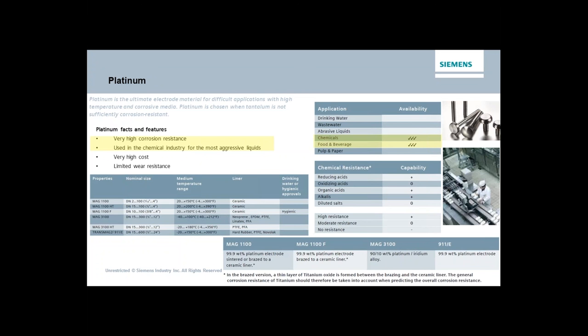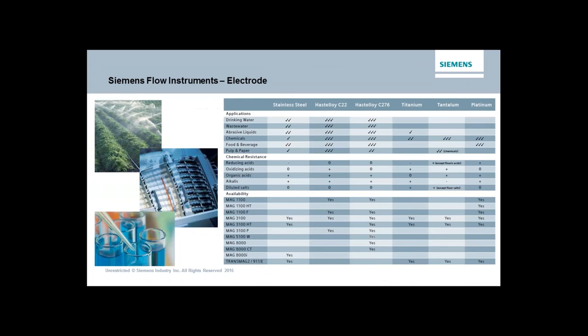You have to be careful when you're looking, for example, at something like a Compass corrosion guide, which is fairly standard, because what they're looking at is pipe. So you're looking at something with a fairly good amount of metal associated with it. If you look at the electrode, you'll see the amount of material on the electrode is not nearly as thick as a piece of pipe would be. So it is possible that you'll talk to a mag meter manufacturer, and they may say, well, we don't recommend this material for this application. And you may have looked it up on a corrosion guide and said, hey, it looked like it was going to work just fine. But then again, you have to remember that the pipe has a lot more material attached to it than the electrode does.